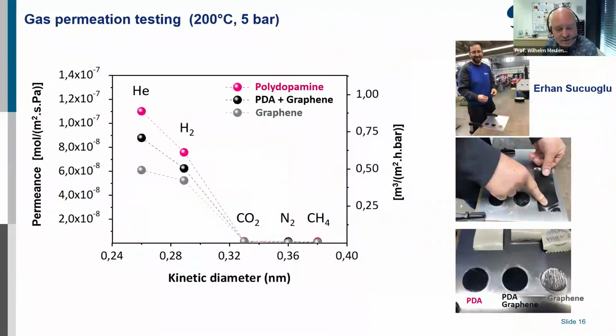And when we make then a gas permeation test, and I have to mention that it is a single gas test, we could observe that at a temperature of 200 degrees, CO2, nitrogen, and CH4 could not pass the membrane. So that means our layers are in the range of the desired diameter. But helium and hydrogen, for example, could pass the layer. And we can also see we made different kinds of membranes here. The pure graphene layer is here, the gray bullets, and the black layer is a graphene layer which we coated on top with a polydopamine layer.